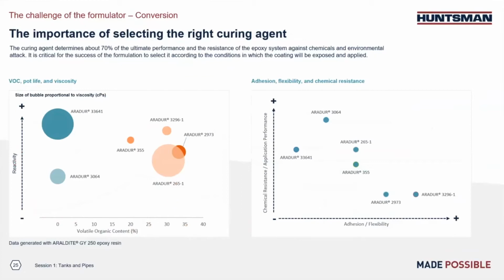And you can see ARADUR 33641 and ARADUR 3064 are both 100% solid curing agents. And we have ARADUR 355 here, which has very good chemical resistance and good resistance to different solvents. It has about 20% VOC content. And we also have another hardener, ARADUR 265-1, and this one has very good resistance to, for example, highly concentrated sulfuric acid. This one has about 30% VOC content.